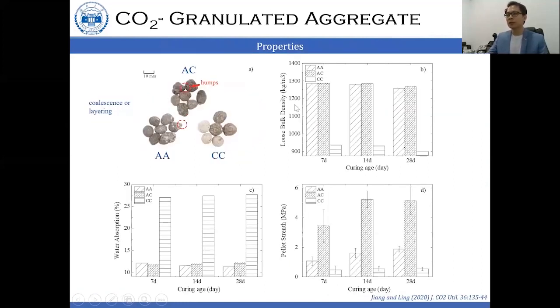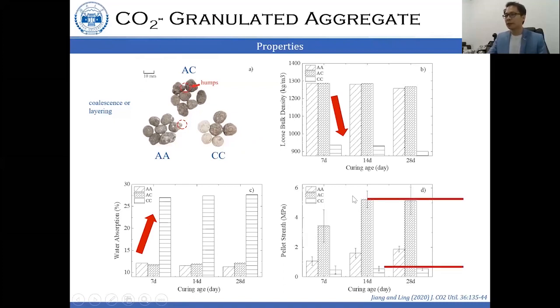So this is some test result for the 3 series of the aggregate. We found that the loose bulk density for the CC aggregate is significantly lower than the AA and AC aggregate. So we can expect they also have the higher water absorptions. And if you compare the pellet strength for the AC, which the aggregate exposure to the CO2 after the granulation, we can attain the strength more than 5 megapascal. However, for the CC aggregate exposure, we are injecting the CO2 during the granulation and also after the granulation. We found that the strength is significantly reduced, only able to have a 12% of the strength of AC aggregate.